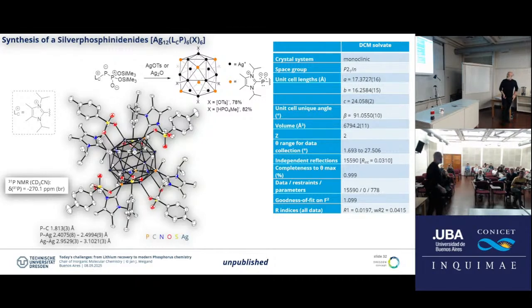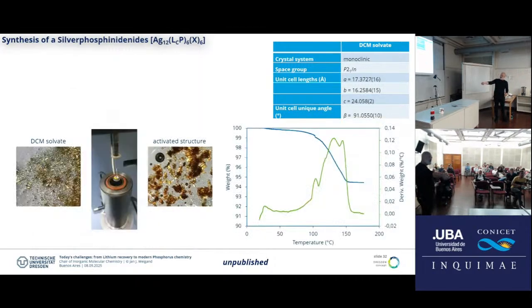And so the solvate is quite interesting because if you put the solvate, beautiful crystals, into the DSC, you see here the DSC, it loses quantitatively all the solvent. So at a decent temperature, 100, 130 degrees is enough, and all the solvate is gone. Now, when we took and investigated these clusters, again, by the way, they are quite air stable, which is also unexpected. For a couple of hours to days, you can keep them on air, not too unstable. Then you look at the material, and it's still crystalline.